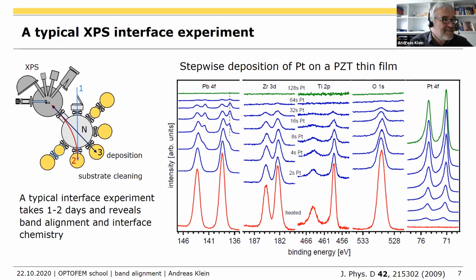She asks whether we can get from a shoulder in a titanium peak. So here's the titanium peak, and if you see a shoulder here, that means you have titanium 3+. This titanium 3+ is a reduced titanium. And if you reduce titanium dioxide, that can be caused by oxygen vacancies, or is very likely caused by oxygen vacancies. So in this case, it makes sense, but you have to be careful. You don't see the oxygen vacancy. You see that you have titanium 3+. This may also be caused in principle by some electron trapping effects. If it's a self-trapping effect, the shoulder does not automatically mean that you also have oxygen vacancies. But for titanium dioxide, I guess that's really good.